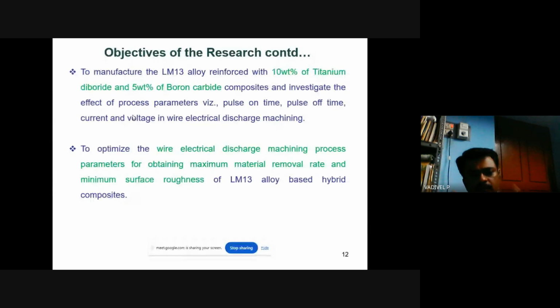And also we have chosen the reinforcement of titanium diboride with 10 weight percentage and boron carbide of up to 5 weight percentage, and investigate the effect of process parameters like pulse on time, pulse off time, current, and voltage in wire EDM. Then optimize the wire electrical discharge machining process parameters for obtaining maximum material removal rate and minimum surface roughness of the LM13 aluminum alloy based hybrid composites.